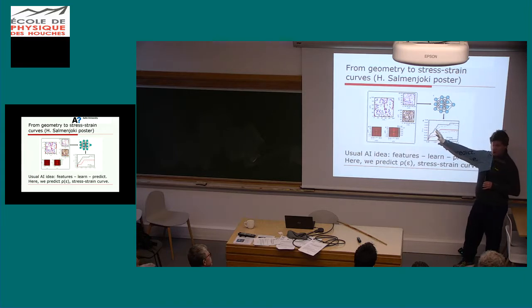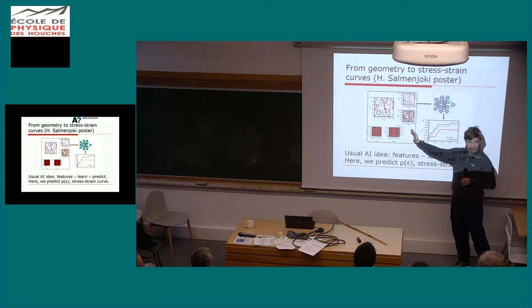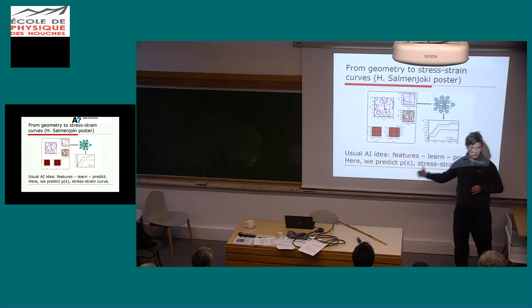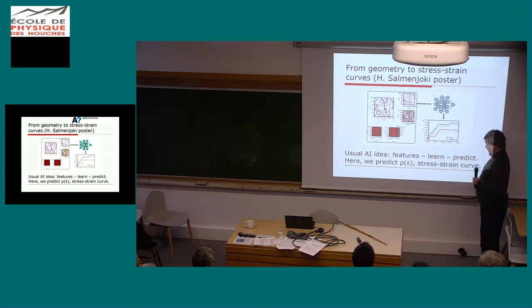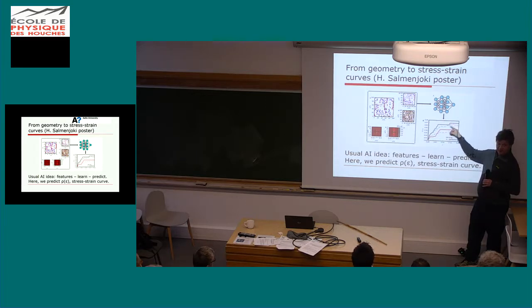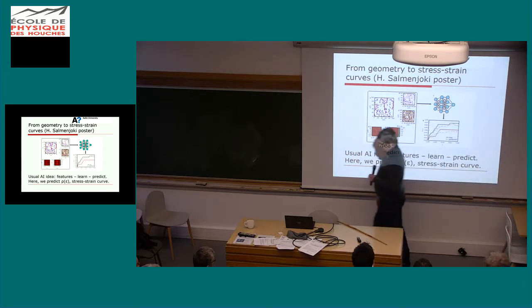a bunch of topological defects at zero external stress, relaxed, and then we can do this exercise in two ways. As you would do with glasses, you would quench in different ways. We did these quenchings in a million ways, and after you do that, you summarize this with parameters that allow you to follow the typical stress strain of a sample. So here is the true one. It has these avalanches, but the average behavior you get from these typical features of the original state actually allows you to guess pretty much what it will do. I can follow the red one as I know what the system looked like at the beginning, without actually applying any external stresses.